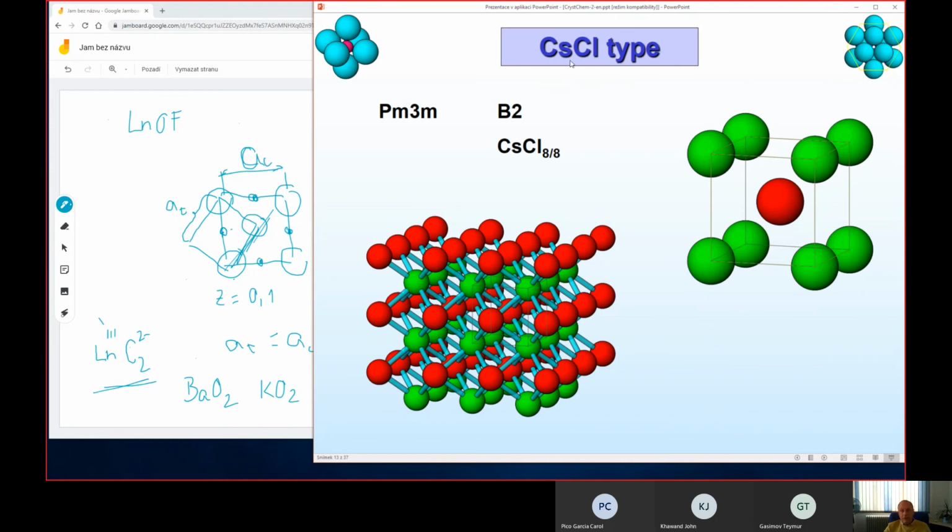Like ammonium chloride, which contains the ammonium cation here. At lower temperatures it is fixed in a certain arrangement, but at higher temperatures the NH4+ molecule can rotate, but it still fills this void or this cubic position.